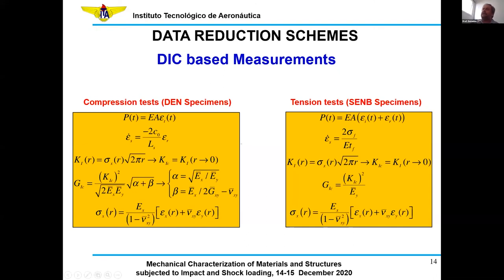Under plane stress conditions, we can convert the stress intensity factor into the strain energy release rate by using this expression that is applicable for orthotropic laminates under plane stress conditions. And with that, we have our intralaminar fracture toughness measured at different strain rates.